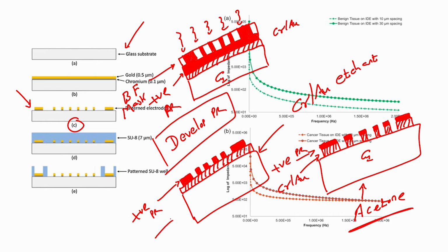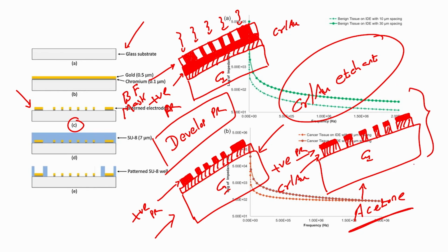I will have this particular wafer where the photoresist in the area which was not exposed by UV will get stronger, and the photoresist where it was exposed by UV will get weaker, followed by which I will dip this wafer in a chrome gold etchant. When I dip this wafer in chrome gold etchant, the chrome and gold will get etched and the photoresist will still be there. Now what I will do is dip this wafer in acetone. Acetone is a photoresist stripper, and when it strips the photoresist, what will happen? We will have this particular pattern which is shown in C.